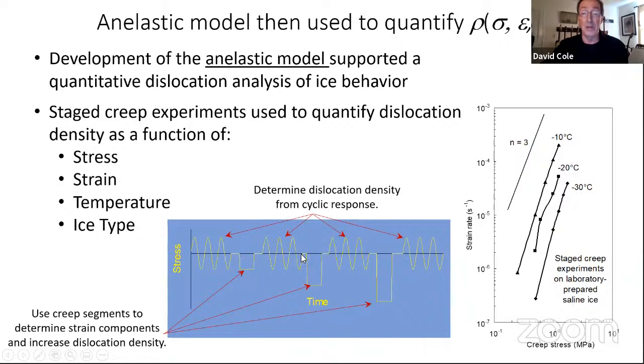Unload it, apply your cycles. Analysis of these guys tells you how much the dislocation density increased. And on we go. This plot over here shows you that doing this stage creep test does in fact produce an n=3 power law dependence. So it gives you a valid test result.